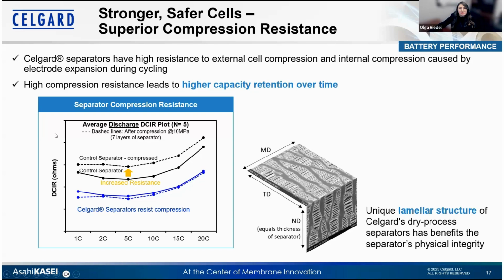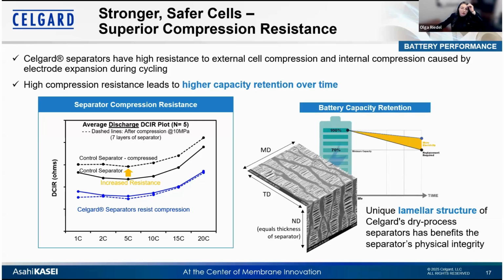This is rooted in our unique lamellar pore structure with this type of polypropylene pillars in between. These polypropylene pillars are similar to a spring in their function. So they help to preserve the structural integrity even under stress. This compression resistance helps maintain pore structure and ionic pathways under high stack pressure, and which also directly supports higher capacity retention over time compared to the conventional separators, which is especially important in very large prismatic hard case energy storage grid cells, while also maintaining, on the other hand, for example, fast discharging rates in UPS systems, even under compression.